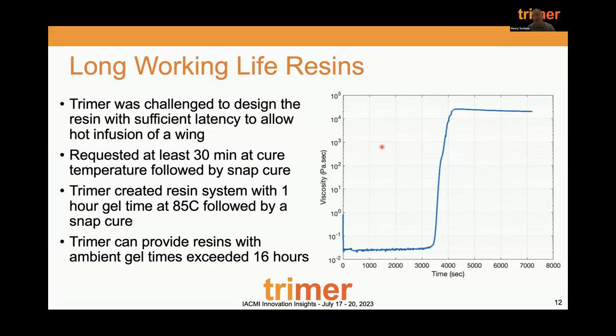So you can actually use hot tooling rather than heating and cooling your tooling. If you think about a wind turbine blade, that very large mold is heated and cooled before the part's removed. This concept is, can we go to more of an automotive concept where you have a hot tool that's never cooled, and you just continually replace parts in it. This demonstrates we have slightly less than an hour before we snap cure, and then a few minutes later it's fully cured and the part's ready to be demolded. So we can do some very exciting things in large-scale manufacturing as well.